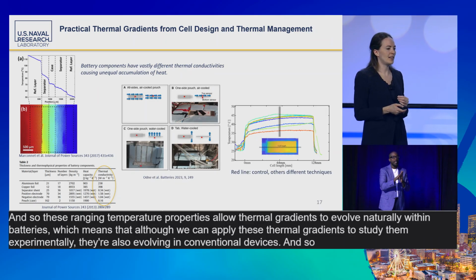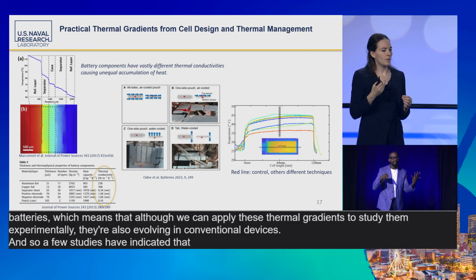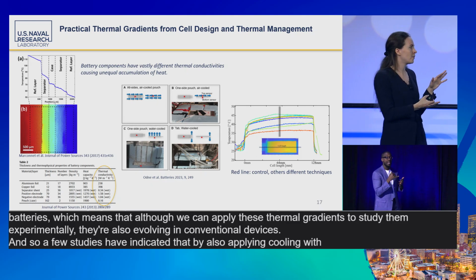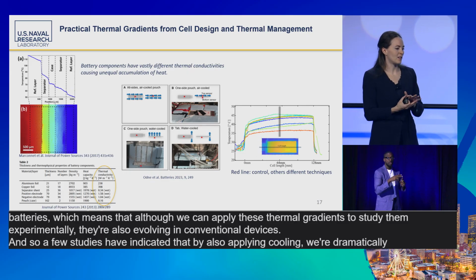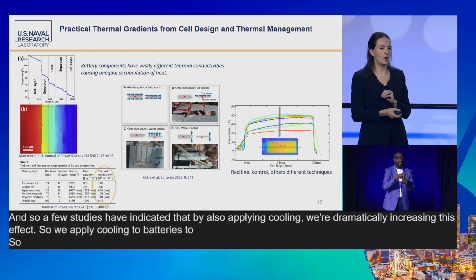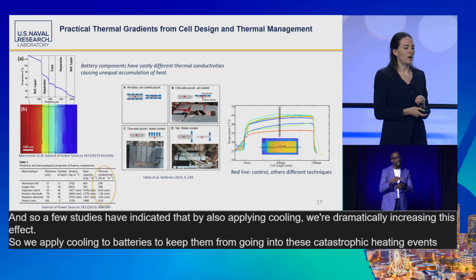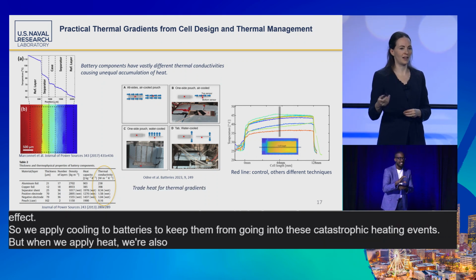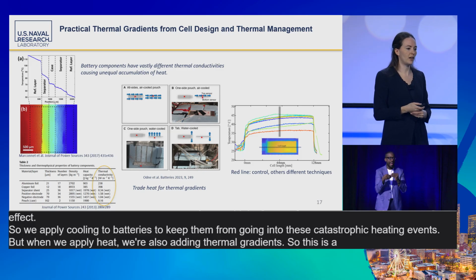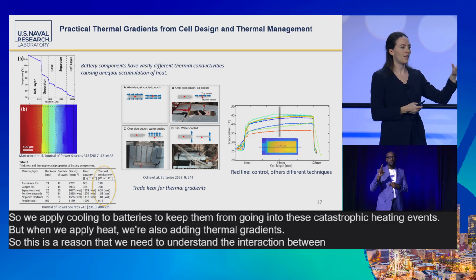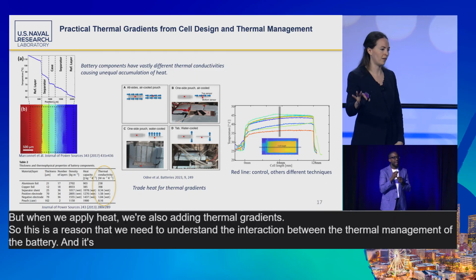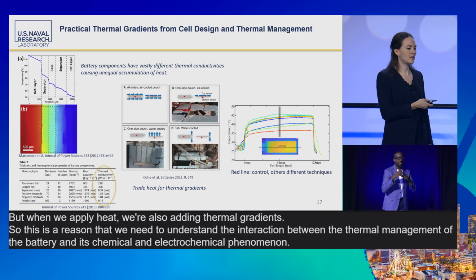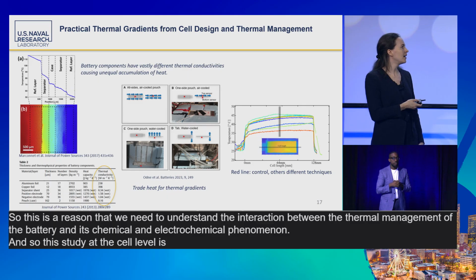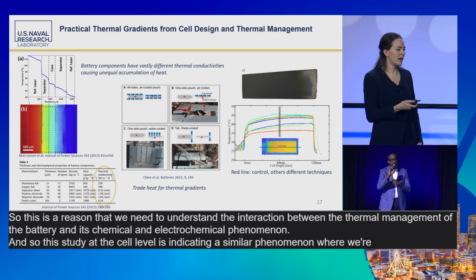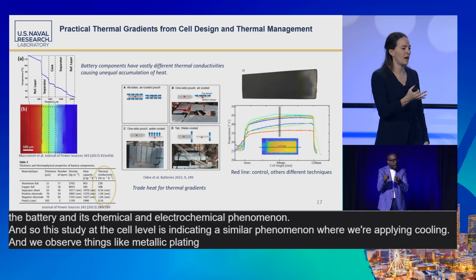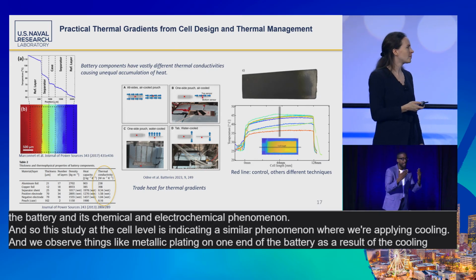And so a few studies have indicated that by also applying cooling, we're dramatically increasing this effect. So we apply cooling to batteries to keep them from going into these catastrophic heating events. But when we apply heat, we're also adding thermal gradients. So this is a reason that we need to understand the interaction between the thermal management of the battery and its chemical and electrochemical phenomena. And so this study at the cell level is indicating a similar phenomenon where we're applying cooling and we observe things like metallic plating on one end of the battery as a result of the cooling geometry.